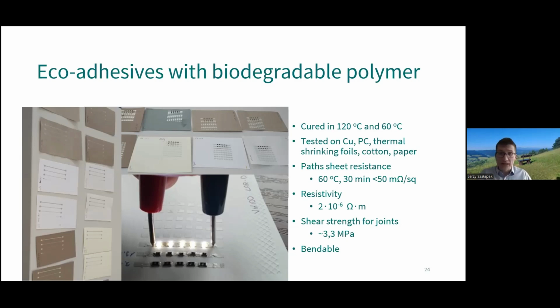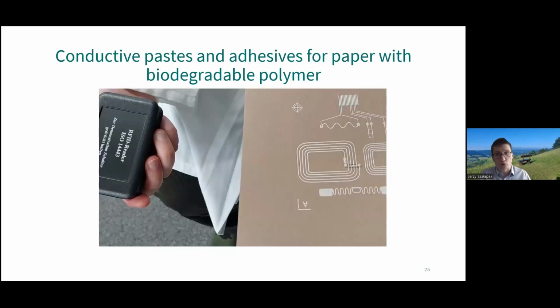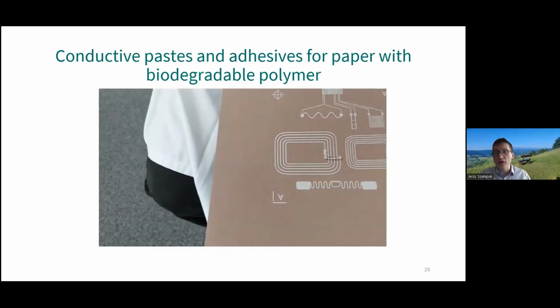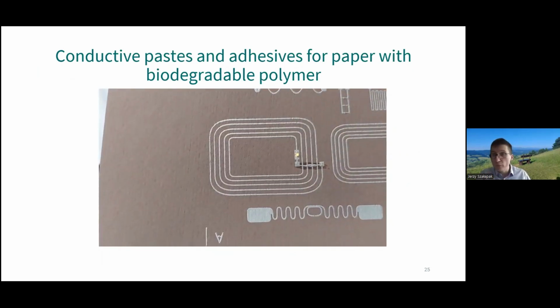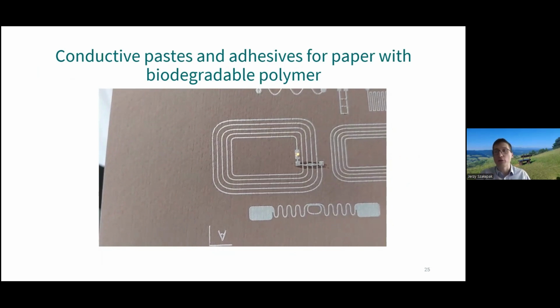After 1,000 bending cycles, the resistance would double. So they're still under development, but initially the research seems quite promising. Anyways, properly working RFID antennas were created. After removing the chip, you can even easily toss such a sample into the fireplace, although I would prefer you use different degradation methods. We have confirmation that proper biodegradation occurs both with substrates and matrices, so the only residue may be a small drop of silver.